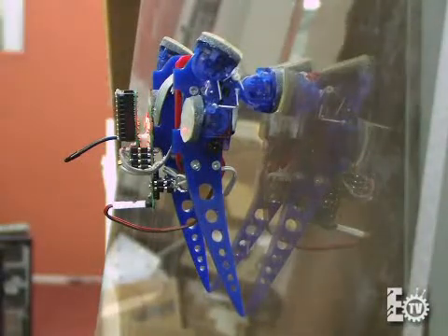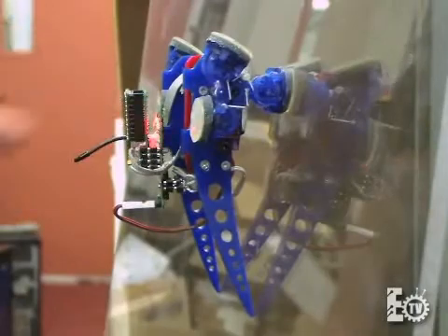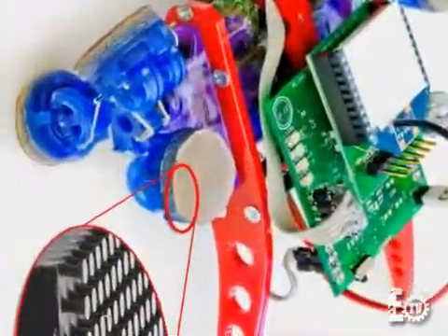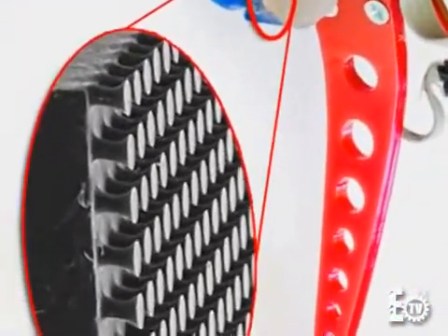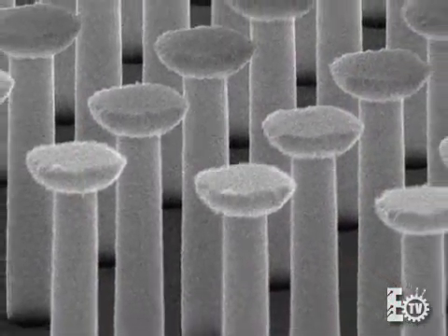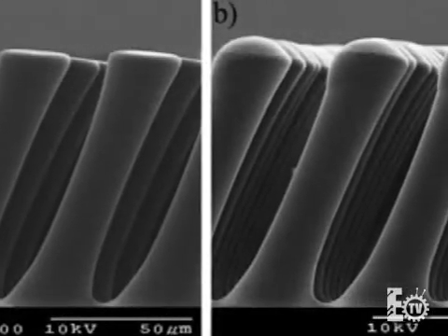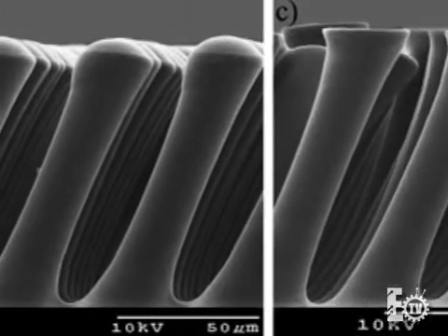The feet on this robot are inspired by the gecko lizard. These pads, although you can't really see it by eye, if you look under a microscope or a scanning electron microscope, you can see that the feet are made up of thousands of very small fibers — very small hairs standing vertically. Each of those fibers has a spatula-type tip, a wider tip. Just like the animal, these fibers can go into surface roughness and make a high number of contacts.